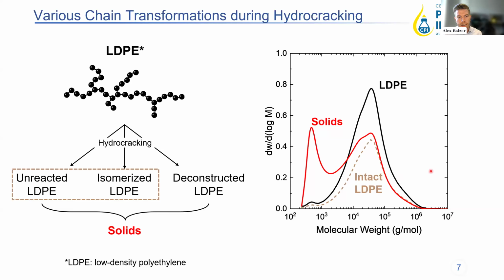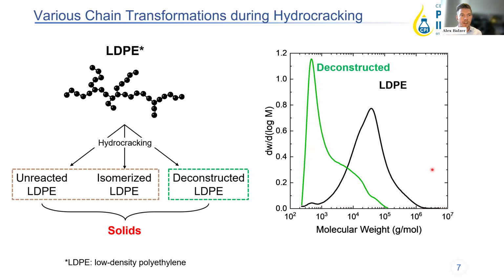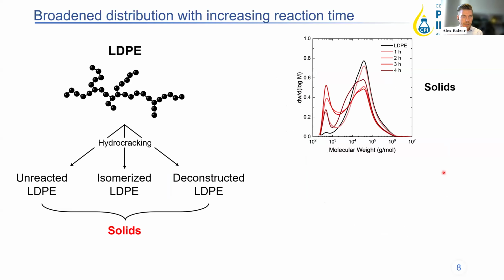From that, we can subtract the intact LDPE from the solids curve, and that helps us understand the new deconstructed chains that exist in this fraction. So these are new polymer chains that exist in the product distribution. So what we did is we tracked both the intact and the deconstructed LDPEs over the course of the reaction.